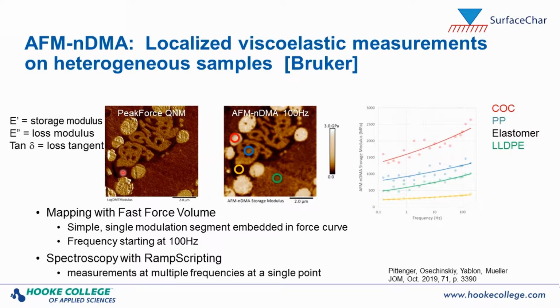And so AFM nano DMA enables you to do 2 different kinds of measurements. You can either map the whole surface at a very fast frequency, at about 100 hertz or higher. And this is giving you now a map of the modulus, either the storage modulus, the loss modulus, or the loss tangent as a function of frequency, again 100 hertz or higher. Or you can do point and shoot, and do very localized measurements with ramp scripting, where you sit on a particular area and then you measure the different moduli.